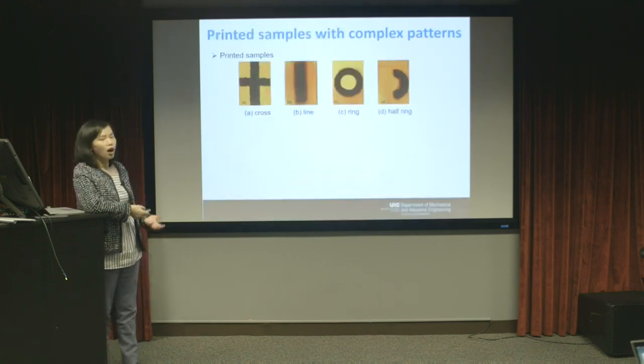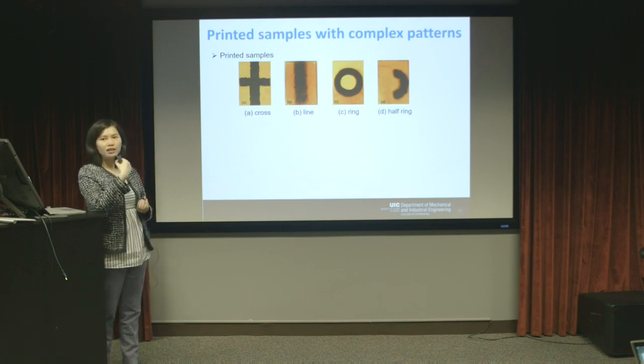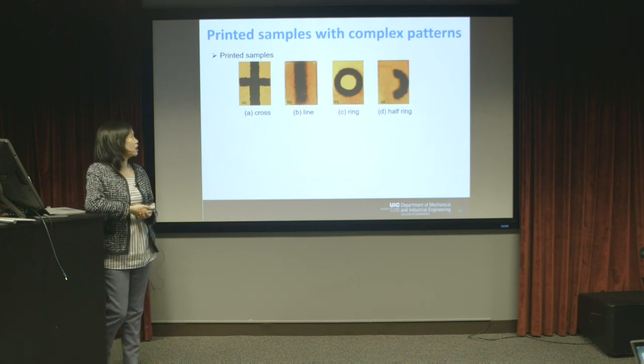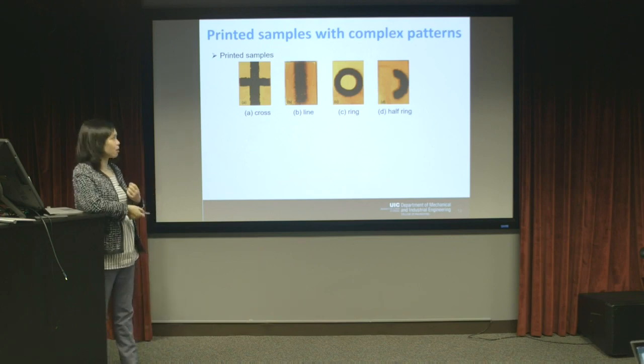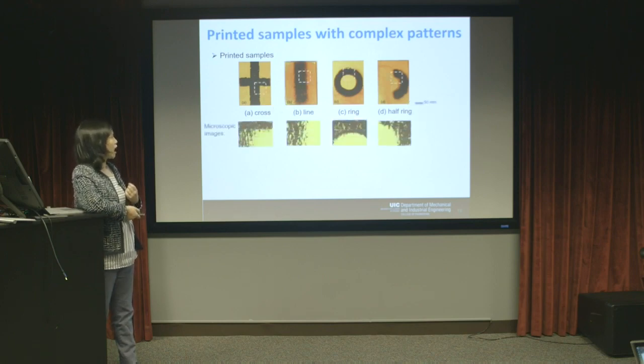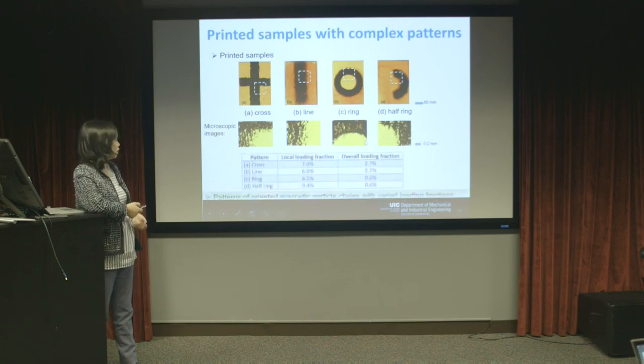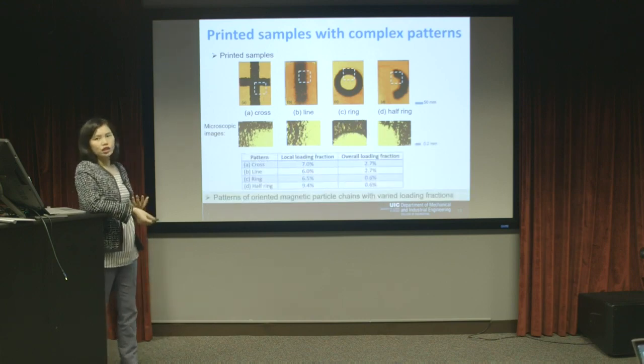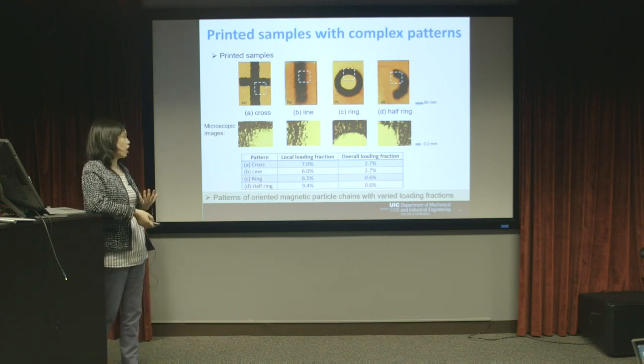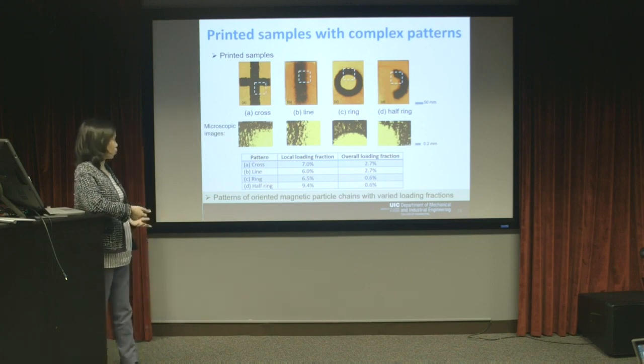And here are some samples. By repeatedly moving the droplet and drawing the pattern, you can achieve very accurate and very dense particle patterns in the liquid resin, and you can solidify it through photopolymerization, such as the cross line and the ring, half ring patterns. And you can see the microstructure of those patterns. Inside the pattern, the particles are formed into chains, and you have a certain chain orientation. With the loading fractions of the particles changed, you can also change the magnetic particle patterns as well.